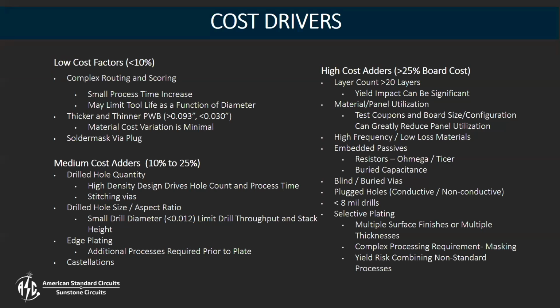We go to the medium adders, and this is where we start seeing some of the higher prices, but very dense drilled designs. When you start looking at 20,000, 30,000 vias on one board, the processing time to drill it really takes quite a bit of time and adds cost to the overall design. Stitching vias are a great example of one use of a lot of vias that typically do tend to take a lot of time on the drill machine. The hole diameter, when you're looking at your overall smallest holes, obviously the smaller the hole, the lower the stack height, so the fewer boards we're able to drill at the same time.